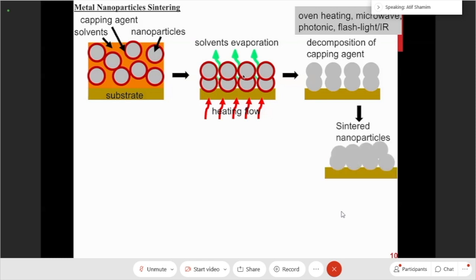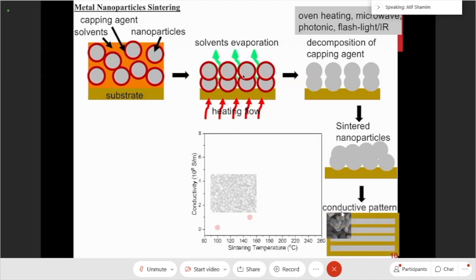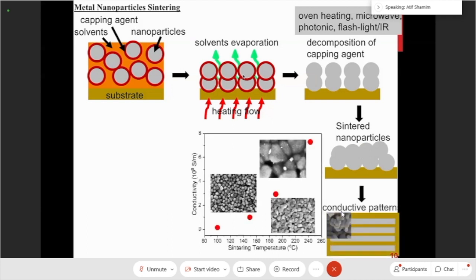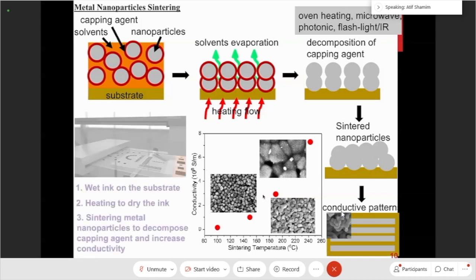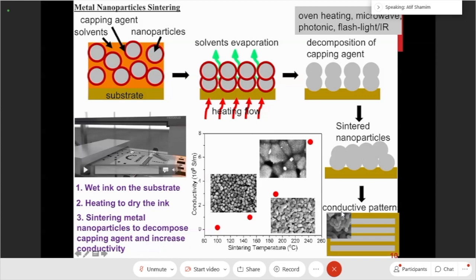Once these sintered nanoparticles start to mix with each other and they start to form patterns, and we'll talk about this metallic ink here, you could see that as the temperature of the sintering is higher, you get better conductivity, which is better mixing of the nanoparticles. Eventually, you could engage this sintering mechanism onto your printing flow mechanism as well.